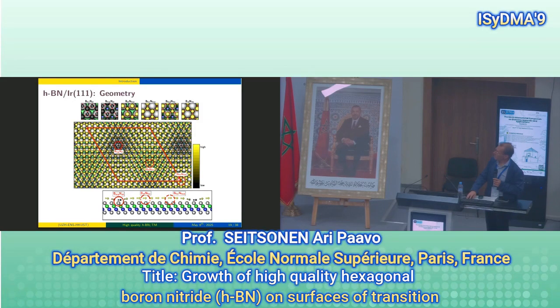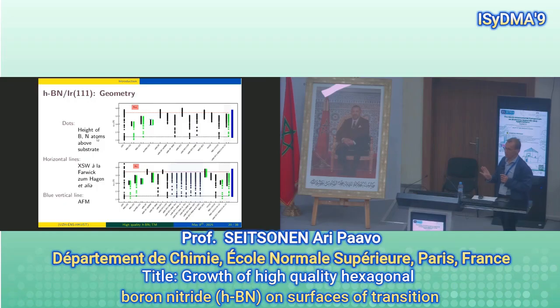And then this is the result of one of the DFT calculations. But the goal was to benchmark the different approximations in DFT, the so-called exchange correlation functional. Those are the different approximations on this axis, so it's just different approximations, there's no continuity. The dots are the height of the boron and nitrogen atoms above the iridium substrate, and the experimental values are the dashed lines.